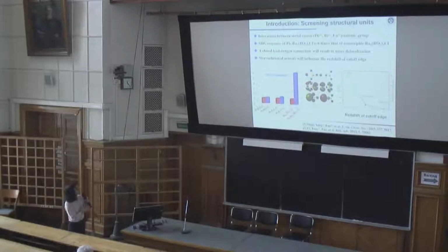Usually we want to scan the structure units, and there are several units we already discussed. So what kind of structure units can be chosen for the deep UV? We first check the first three structure units. Firstly, we check the lone pair effect, and there are some systems. For the first system, the SHG enhancement is not higher, almost the same as the isostructure. But for the third system, the SHG enhancement is very high, almost 6 times that of the isostructure for these compounds.